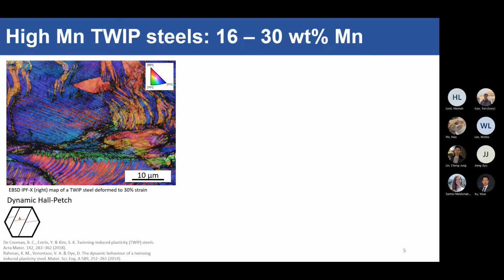And what these twins do is that they continuously fragment your grain. So you keep chopping up the grain into smaller and smaller parts in what is called the dynamic Hall-Petch effect. So if you look over here, so you start strain, you form twins, and they really refine the dislocation mean free path. And you strain it some more, you got more twins, and then you activate a second twinning system. At the end of the day, your mean free path is so small, dislocation finds it very hard to propagate, and that's where you get strength from.